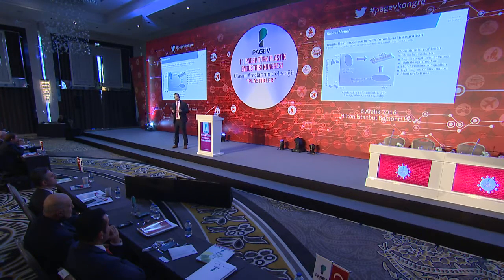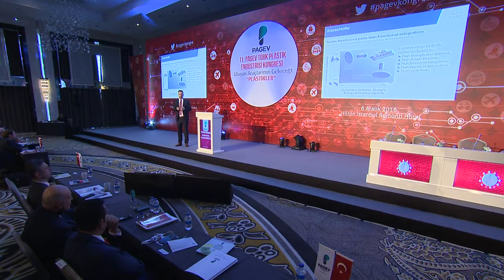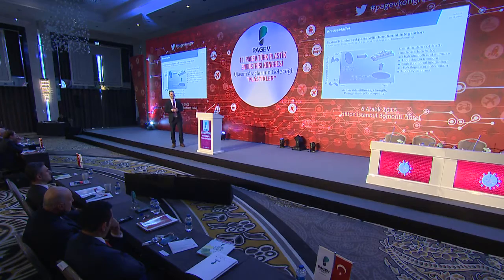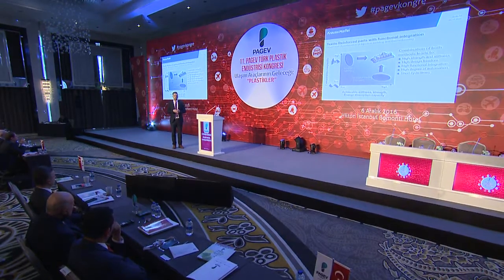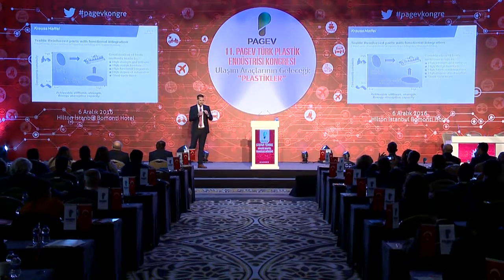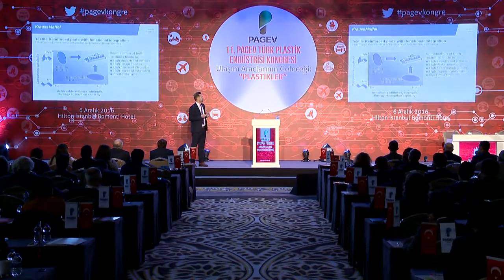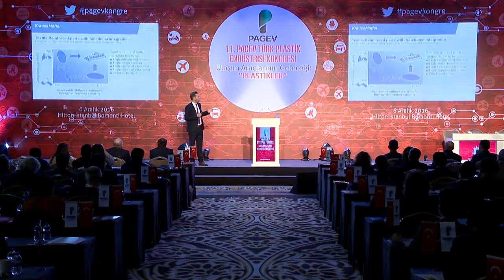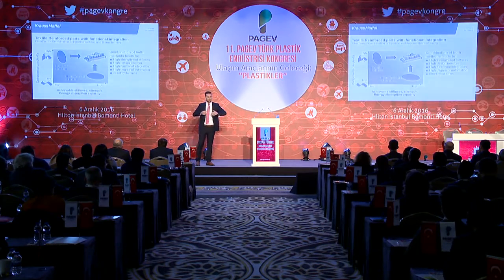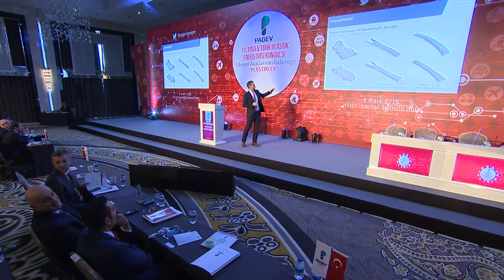Let's switch to the Fiberform technology, which is now a thermoplastic lightweight technology at KraussMaffei. What we do with Fiberform, we combine the injection molding together with the thermoforming of textiles. And here we try to make the best out of two worlds. The injection molding process gives you excellent component complexity, but as I said in the beginning, only limited mechanical properties. The thermoforming of textiles gives you very good mechanical properties, but at the same time, the component complexity is limited. And with the Fiberform technology, we try to make the best out of these two worlds.